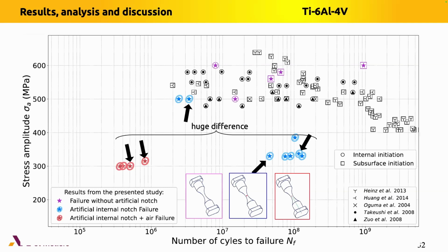The results in black are results from literature on the same titanium alloy. So first, we can see that our results without the defects, the purple symbol here, are in agreement with the literature. But the most interesting thing is to look at these results. If you compare the specimens loaded more or less at the same loading level, around 310 megapascal, we can see there is a big difference in the fatigue life between the specimen with the internal defect and air inside the crack and the specimen with internal crack without air. And we see that the fatigue life is very, very reduced when you put air inside the specimen. So we try to understand that.